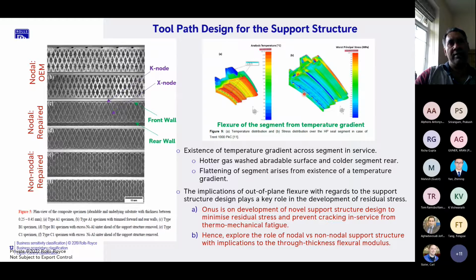Because of this flattening and unflattening, you get residual stresses that build up within the abradable, because keep in mind this abradable has been additively built. So in addition to the pre-existing stresses that would have existed after you build it, you additionally get stresses that form because of this thermal flattening and unflattening in service. So one of the important things we want to ascertain in this repair project is, we have a pre-existing design of the abradable, which is this nodal design. Number one, is it possible for us to develop an alternative design such that the residual stresses, both during build as well as during service, are lesser, which would mean that the abradable will have a longer life on the segment? And if that is the case, how do we actually approach this?